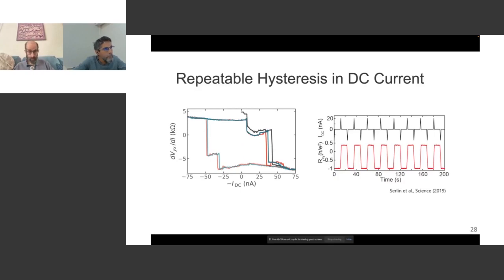And it turns out that this magnetic switching occurs at current densities that are 3 to 4 orders of magnitude lower than any other case that people have shown for electrical switching of magnetism.